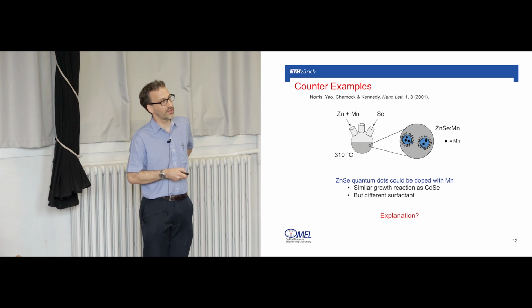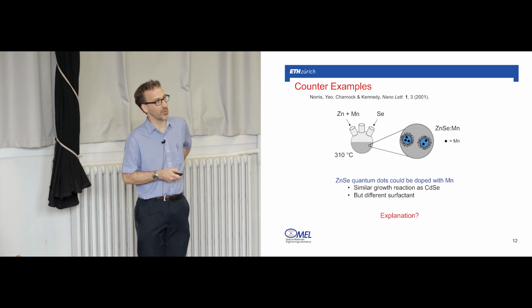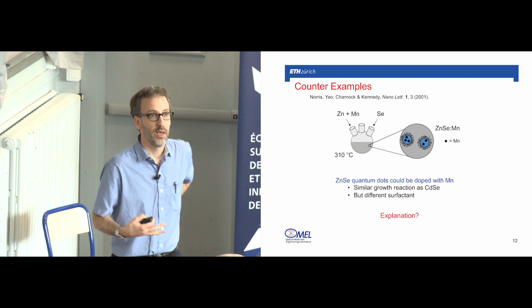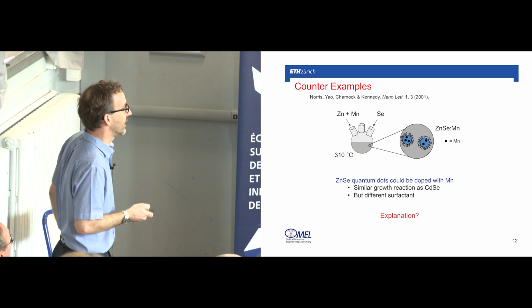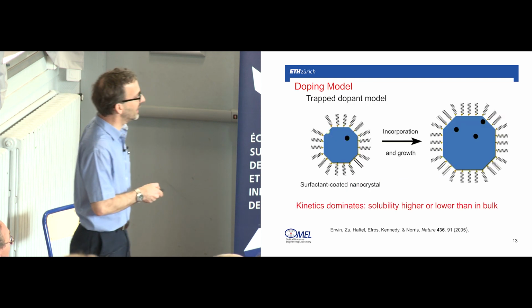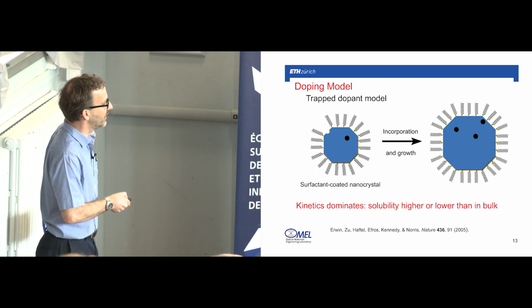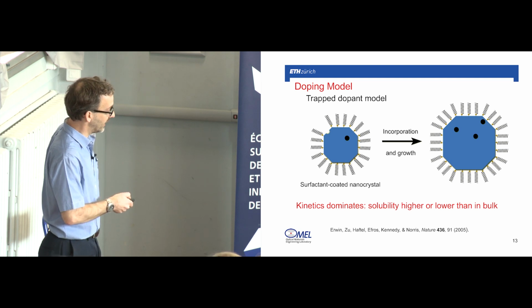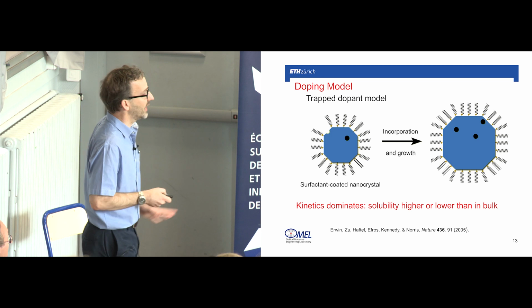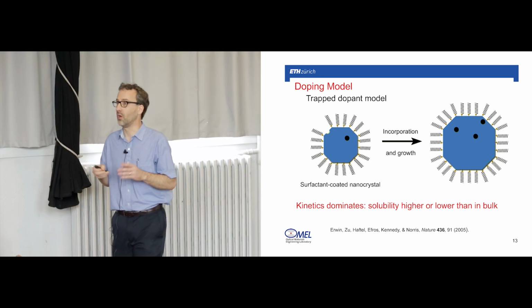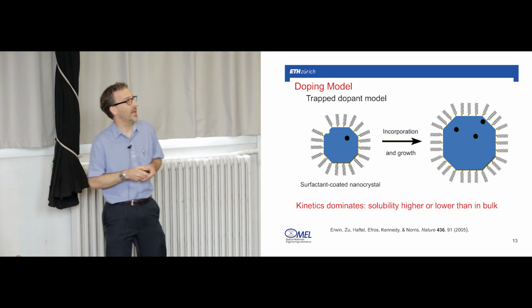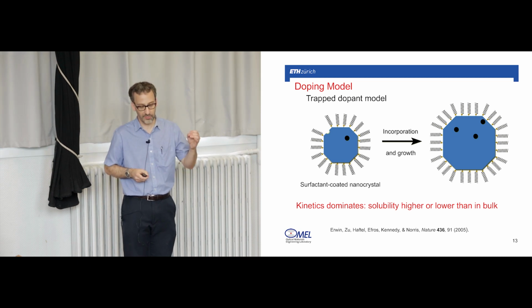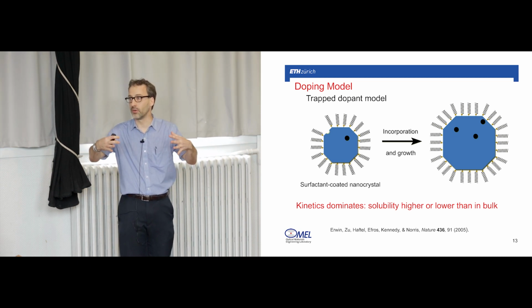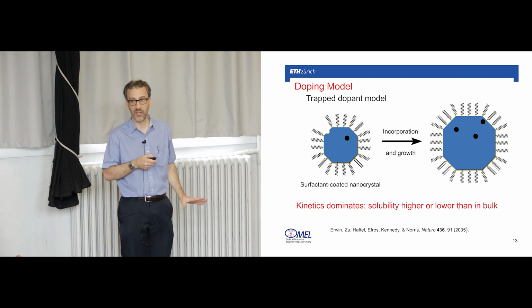But anyway, what's the explanation in broader terms? Why could we dope zinc selenide and not cadmium selenide with manganese? After a lot of work with Steve Erwin, who does density functional theory at NRL, Lijun Zhu, a very talented synthetic student of mine, and Sasha Efros and Tom Kennedy, we came up with a model that we thought could explain all of these disparate results. And instead of using self-purification, which again is a thermodynamic model and requires diffusion, we thought about kinetics.